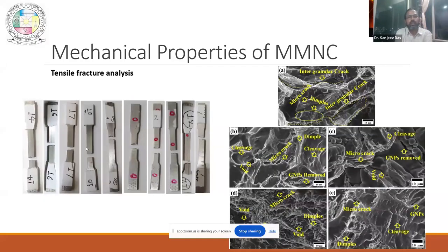Now let us see the mechanical properties, where we have done the fracture surface analysis. So we have done all the fracture surface analysis. Most of them show cleavages, a very small amount of dimples, and some cracks are formed. So, as you have seen, we don't have much elongation there. The dimples are less, ductile failure is less, and you are having more brittle type of failure. This can be further improved if we do some amount of working or some amount of heat treatment on it. We can get rid of it and we can improve the ductility. So those things we are in the process of developing or improving by other mechanical means. We are trying to do it.